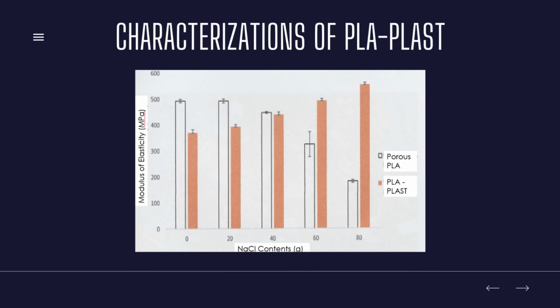Third, it showed the effect of NaCl content on modulus of elasticity of porous PLA and PLA plus. The modulus of elasticity of PLA plus increased when the NaCl content increased, while the modulus of elasticity of porous PLA decreased. The NaCl content greatly influenced the formation of pores. The increase in modulus of elasticity due to the pores that has been impregnated with PDMS and produce high interconnectivity between matrix and pores.